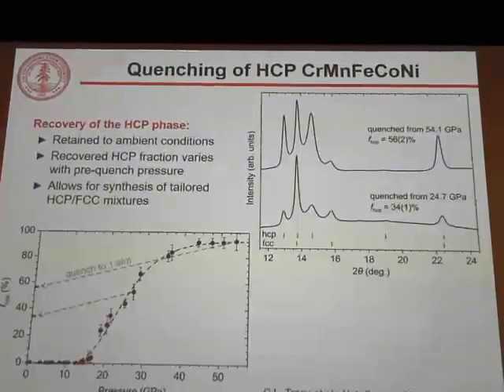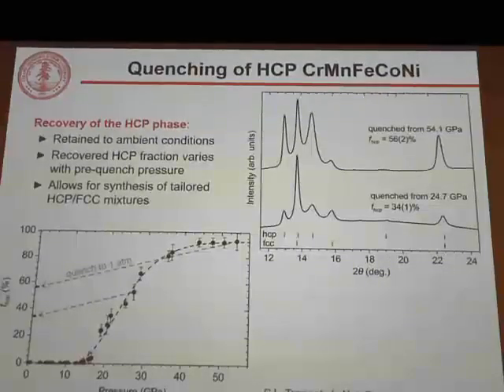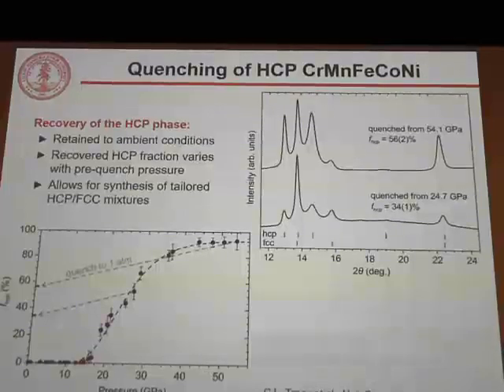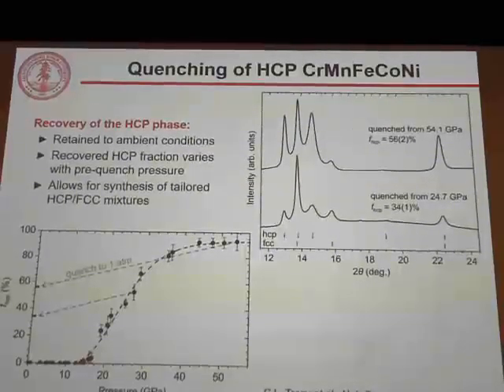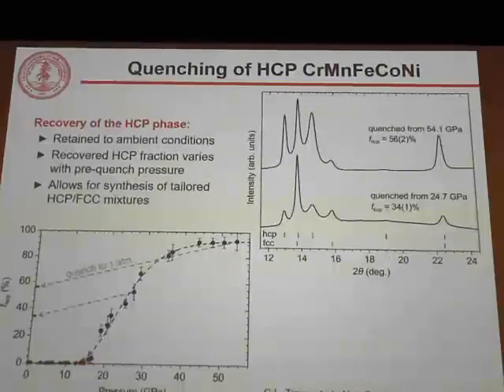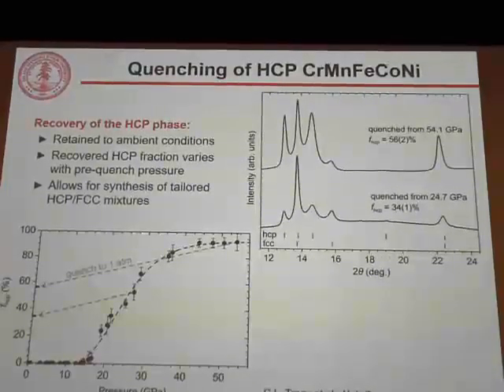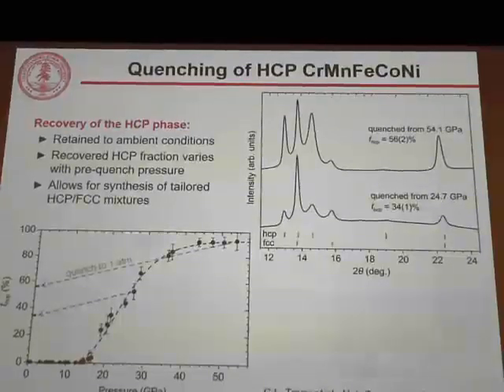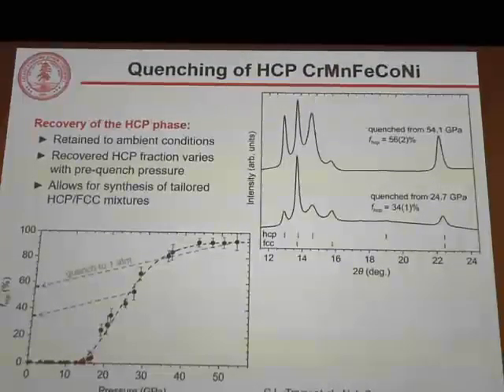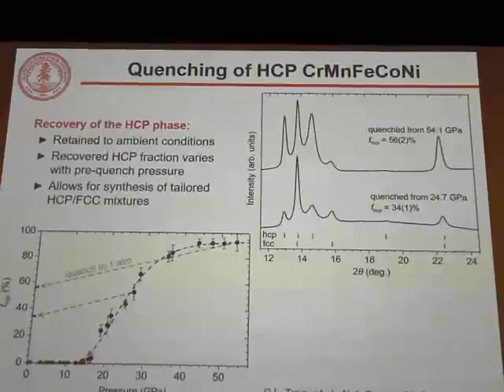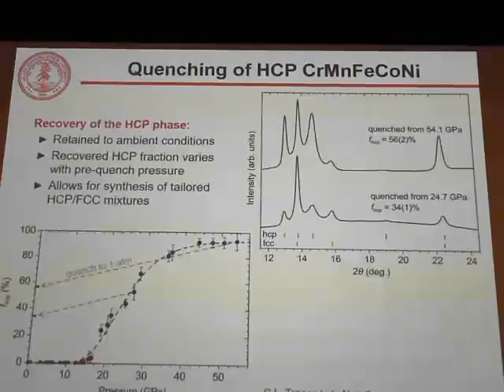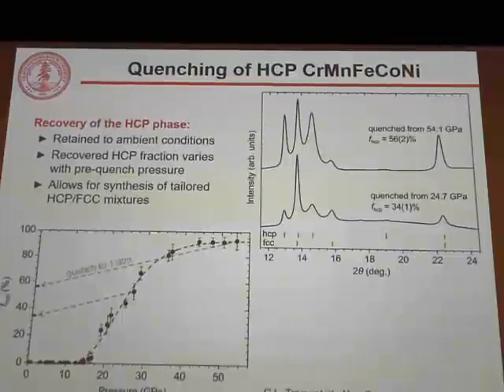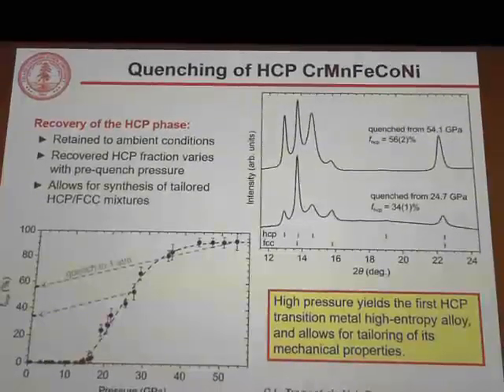I show here on the upper right XRD data for materials quenched from 54 GPa and 25 GPa, and we see that there is quite a lot of signal from an HCP phase, even after we've removed the pressure. And as I show on the bottom, the HCP fraction, which you end up with, is proportional to the pressure you achieve when you pressurize the material, meaning that we can tailor mixtures of the hard HCP and ductile FCC phases, meaning that we can tailor the mechanical properties of these alloys.